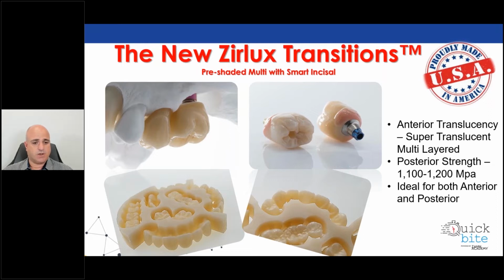That's been a challenge up to recently. I'm happy with the transitions because it really mimics not only the way natural light behaves with the tooth, but also the way it's formulated and manufactured. It's manufactured in a transition whereby from the cervical, there's a greater level of chroma, and as it gravitates towards the incisal edge, there's a balance rather than lines of demarcation with multi-layers. There's a balance that your eye cannot decipher, and it transitions all the way to the incisal edge where you get the most amount of translucency. It's really an incredible translucency, and again, different than the typical zirconia we're accustomed to, because it behaves more like ceramic, more like glass, with more natural opalescence.